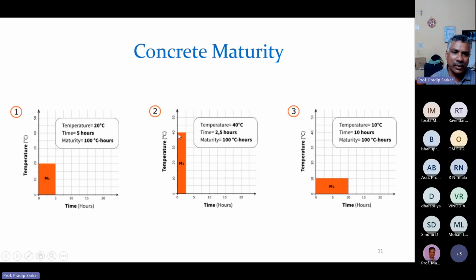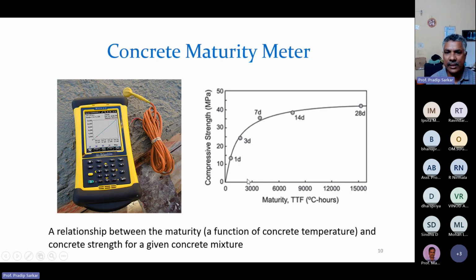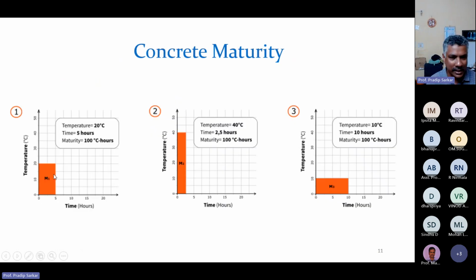Here we have a constant temperature of 40 degrees. This is the internal concrete temperature, but over a time of 2.5 hours, it is also the same maturity. So the same maturity, 100 degree centigrade hours, for all three cases. But in the first case it is 5 hours, in the second 2.5 hours, and in the third 10 hours. This same maturity, if you see in this curve, represents the same compressive strength. In 5 hours this compressive strength is achieved, here it is achieved in 2.5 hours, and here the same compressive strength is achieved in 10 hours. So it is related to the temperature-time history.